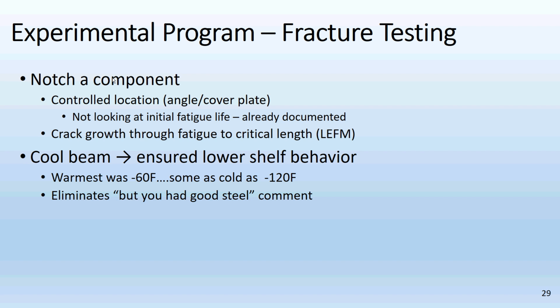Now you probably think, well, why would you do that? Well, some of the steels we used were from old girders, so they were not so great. They would be tested at minus 60. But some of them were newer steels, and so they had more toughness. What we wanted to make sure was that all of the girders were tested when the fracture would occur on what we're going to call lower shelf. In other words, single-digit foot-pounds.